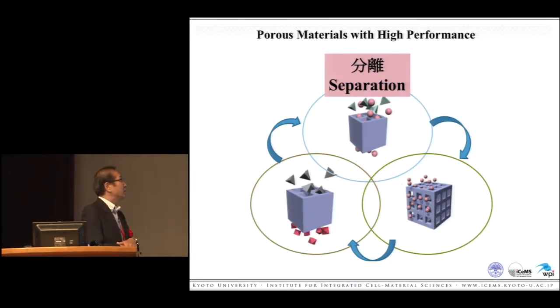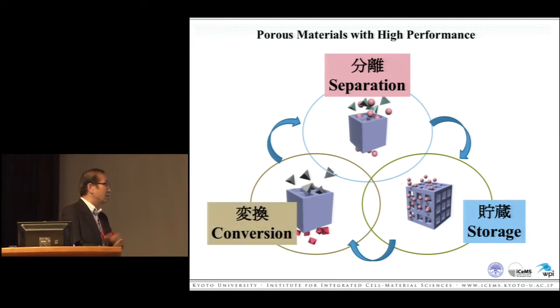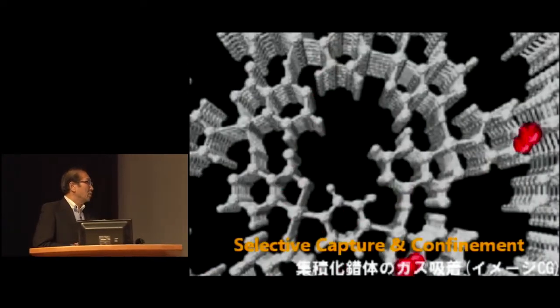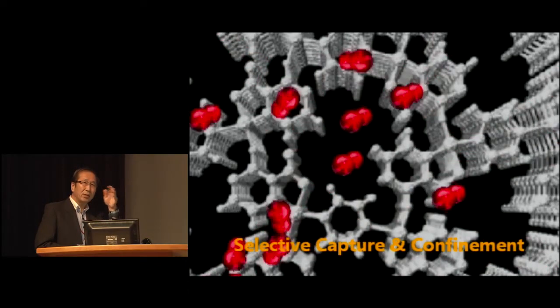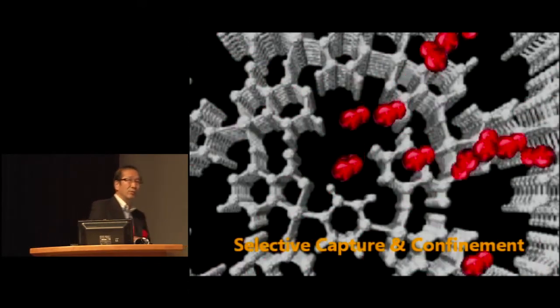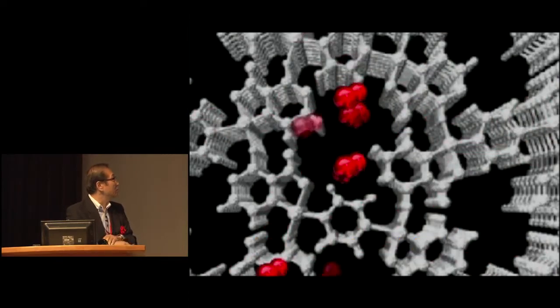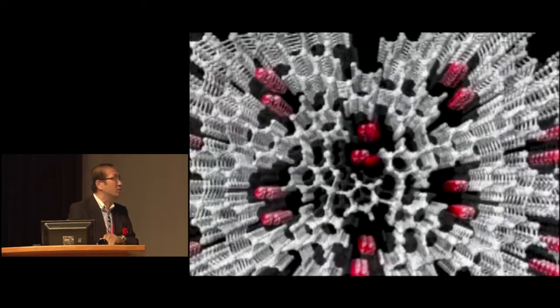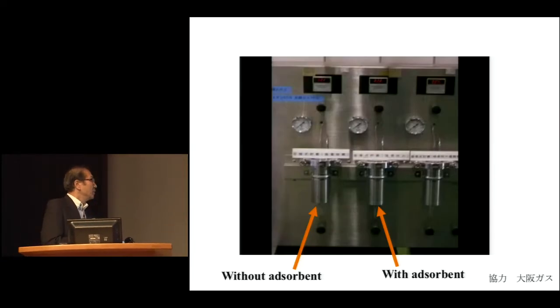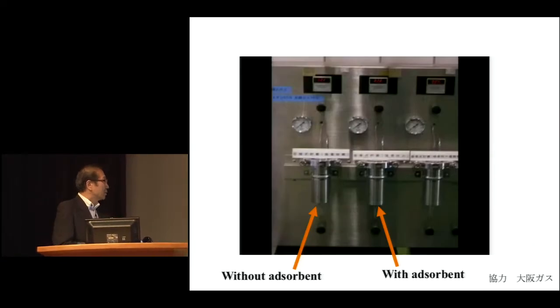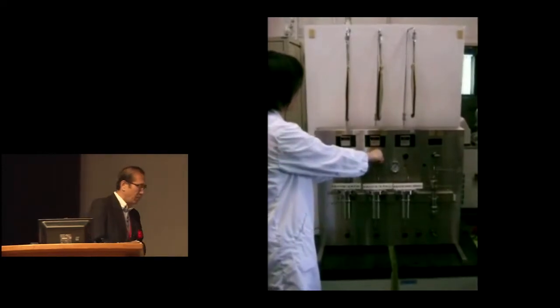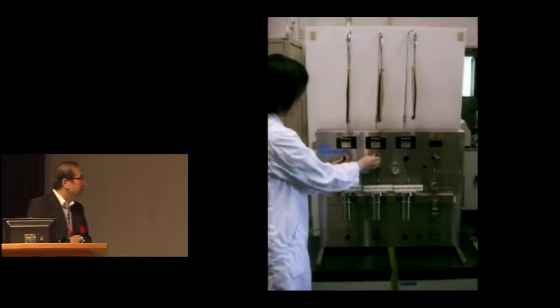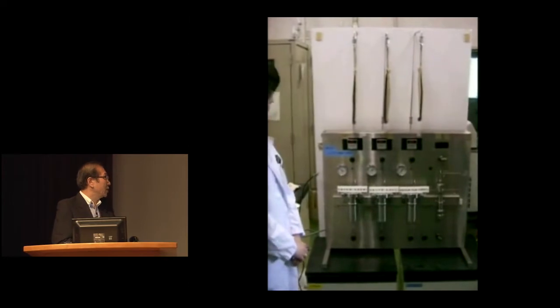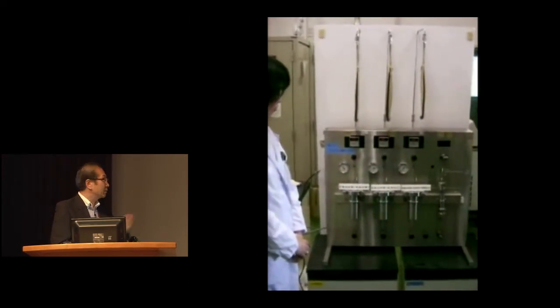Then what functions do they have? Separation, storage, and conversion. What about storage? A function of storing. Such a material is made of a lot of pores, made of metallic ions and organic molecules. This cylinder contains our material, MOF, and the other doesn't. Then we introduce CO2 in these 2 cylinders, at the same pressure, 5 bar.